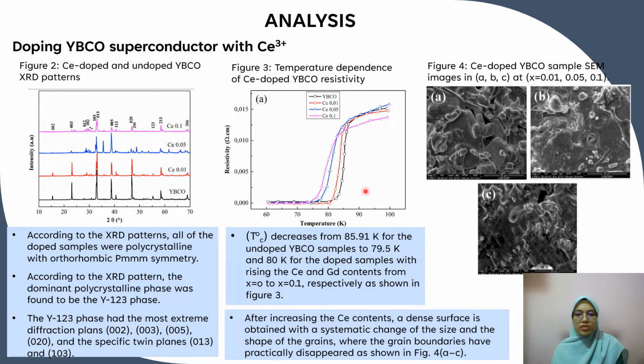Figure 3. Figure 4 shows the Ce doped YBCO sample SEM image in A, B, C at x equal to 0.01, 0.05 and 0.1. After increasing the Ce contents, a dense surface is obtained with a systematic change of the size and the shape of the grains, where the grain boundaries have practically disappeared, as shown in figure 4A until C.